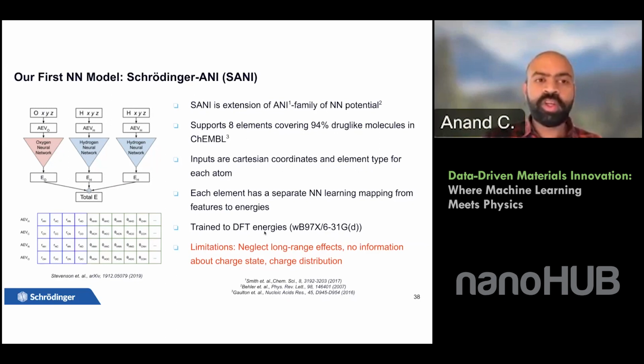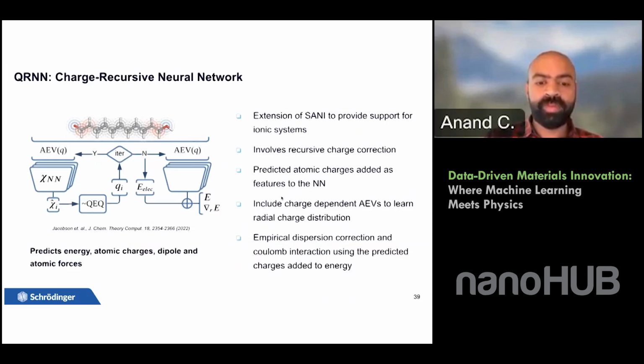But the problem with this first generation of neural network model is that it neglects long range effects. It doesn't predict any charge, and it doesn't have any empirical charge correction as well. So we came up with a new architecture called QRNN, which is an upgrade on the SANI architecture. It also recursively predicts the charges on the atoms and equilibrates them during the prediction process. And we are predicting not only the energy, but also the forces, and we are training on the energies, forces, and also the charges. And once you're able to predict charges on the atoms, we can actually use empirical dispersion correction, and we can calculate the Coulomb interaction and add those contributions to the energy of the system.